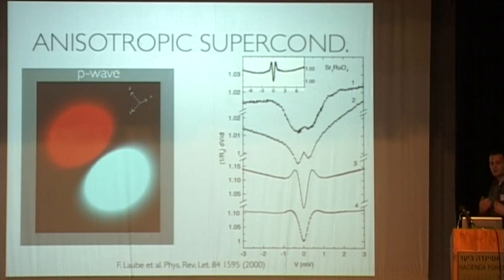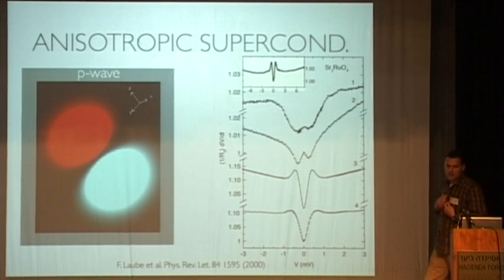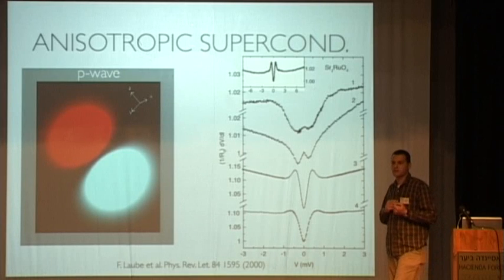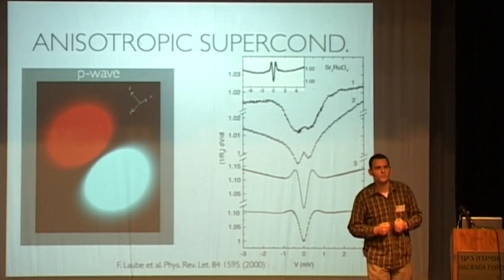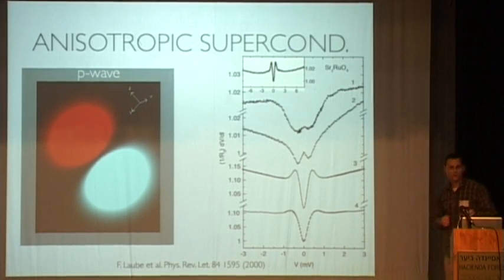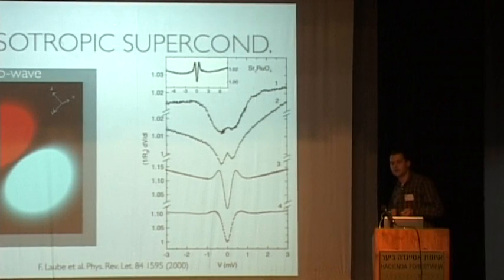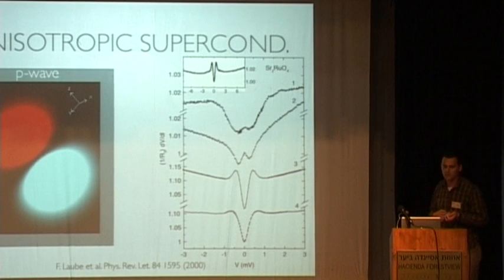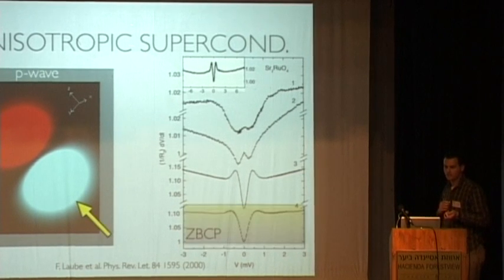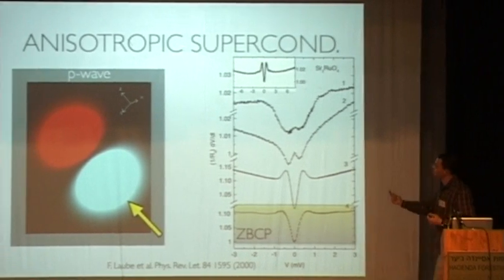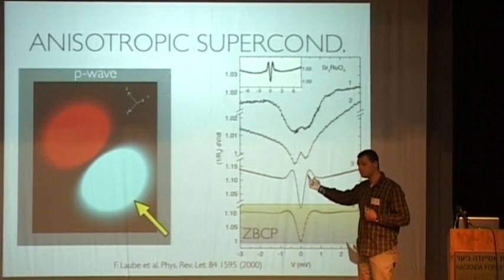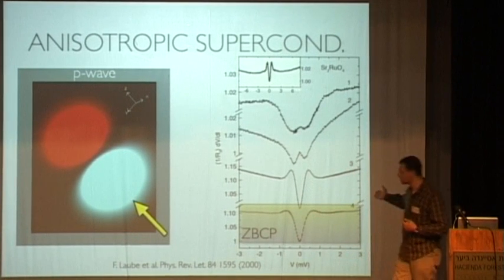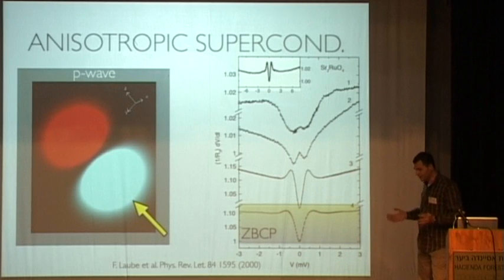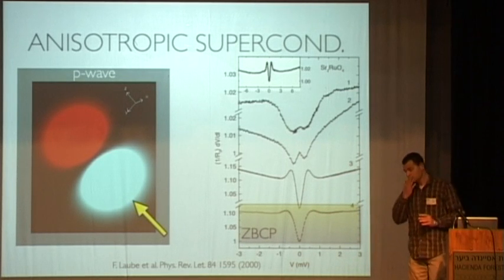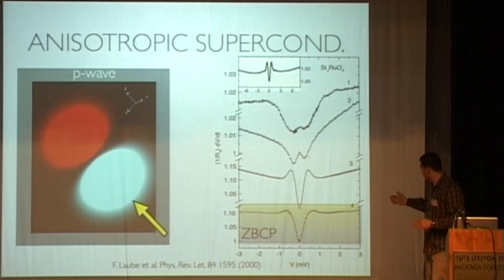So, and why do we care about it? A lot. We care about it a lot because it should affect the transport properties. For example, here on the right you see measurements of a material called strontium ruthenate, which is a known P-wave superconductor. And for example, if you inject electrons from that direction, you measure some kind of profile of the conductance. In this case, it's a zero bias conductance peak.